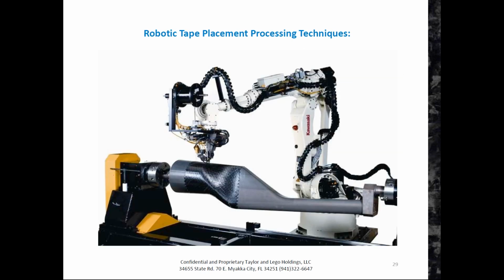Another process is kind of a hybrid between the filament winding process and some of the latest, greatest robotics technologies: the robotic tape placement processing methods. This is a 6-axis robot doing a highly contoured tubular structure, and it's applying carbon tape. That tape can be impregnated with thermosets, so it can be epoxy, it could be vinyl ester, something that you ultimately cure by heating in an oven, vacuum bagging, or autoclaving the part after it's been applied to a mandrel.